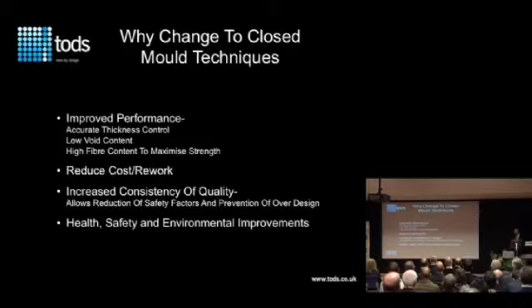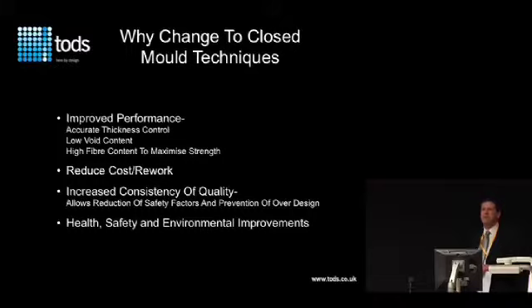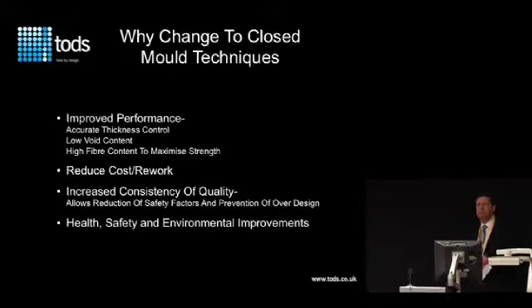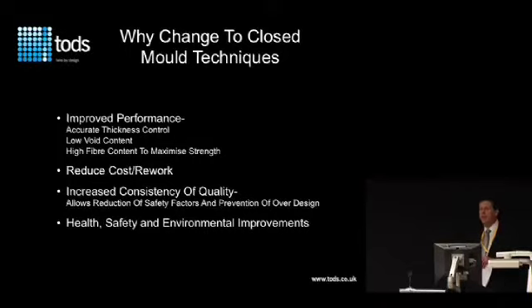Really what we're looking for, I suppose one of the overall criteria, is we don't want to increase costs. If we can reduce costs, we're interested in that, but mainly it's about improving the performance of the products that we make. So by going to closed mould techniques, you get better thickness control, lower void contents, higher fibre contents to maximise your strength. We've found that these techniques reduce costs and rework, and because of the increased consistency of the quality, you can reduce safety factors, which prevents over-design, keeps your cost to a minimum. And also, if you're using particularly polyesters, vinyl ester resins with open moulds, you've got health, safety and environmental issues.